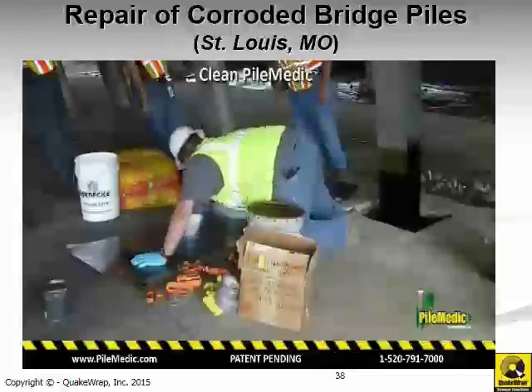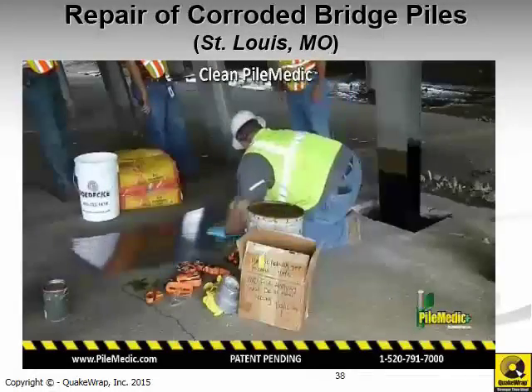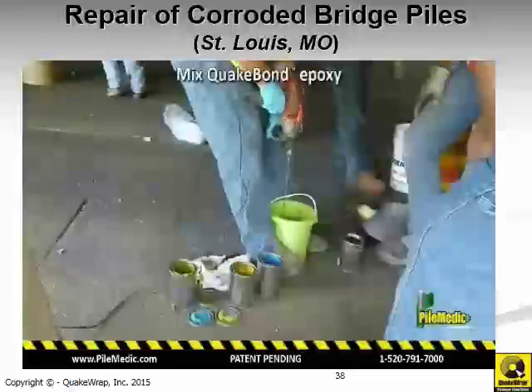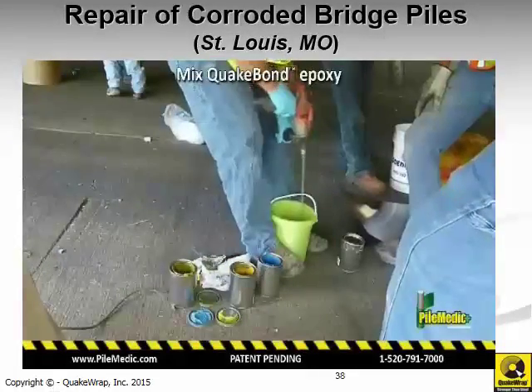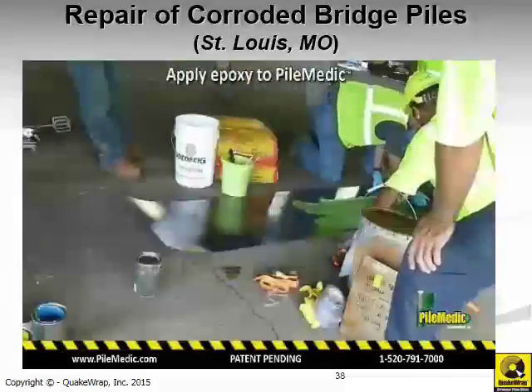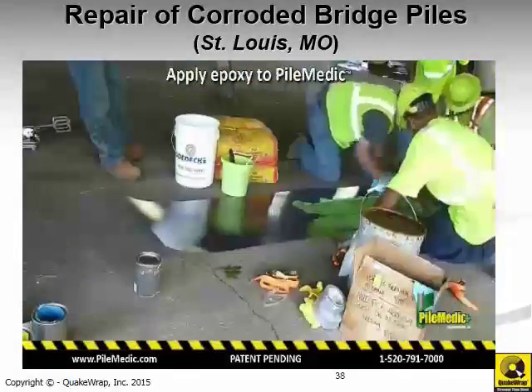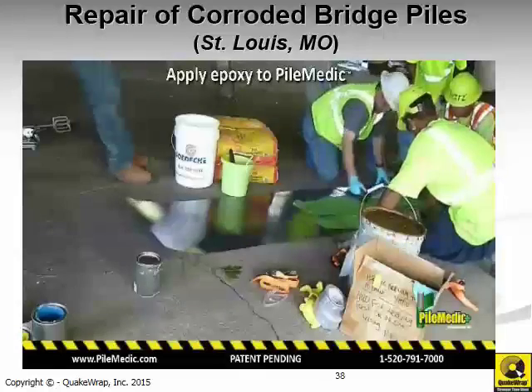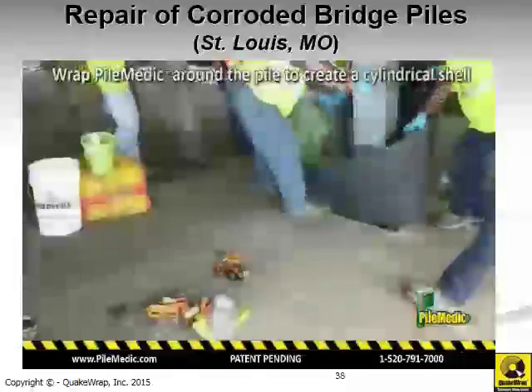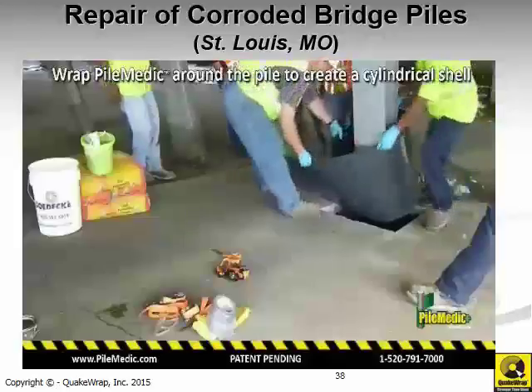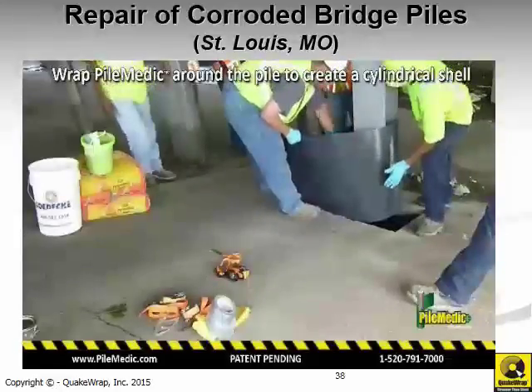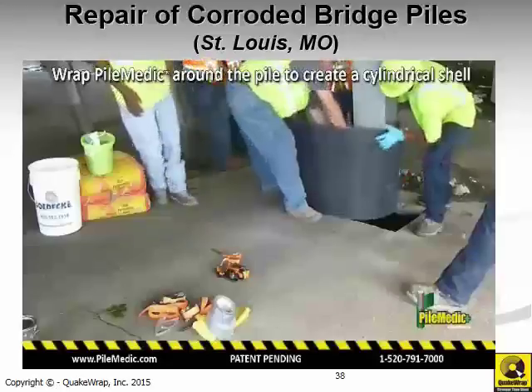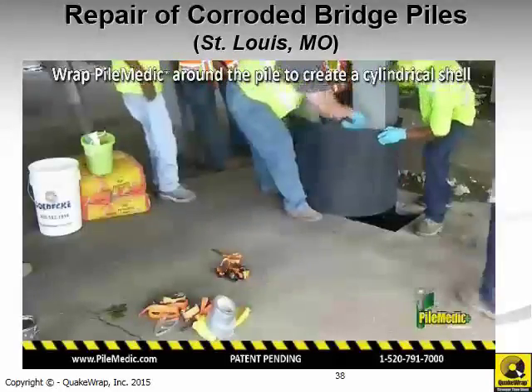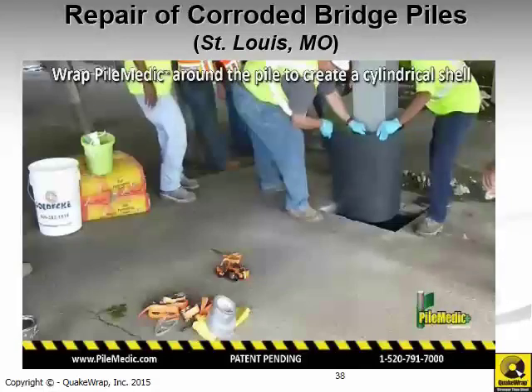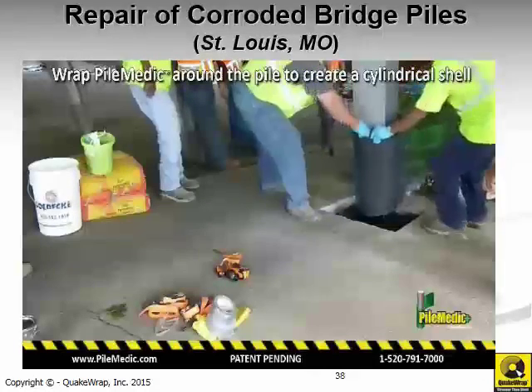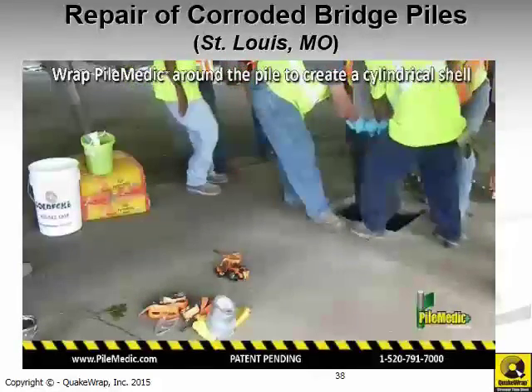The next thing is the worker has cut a section of this PileMedic laminate, 2 feet wide by about 12 feet long, and we mix this epoxy and put that on one half of this laminate, which is the second wrap. As we wrap this around, the first layer, which is against the column, is not stuck to the column, but that second layer that has the epoxy on it gets glued to the first layer. So by this approach, we create a 2-ply shell around the column.